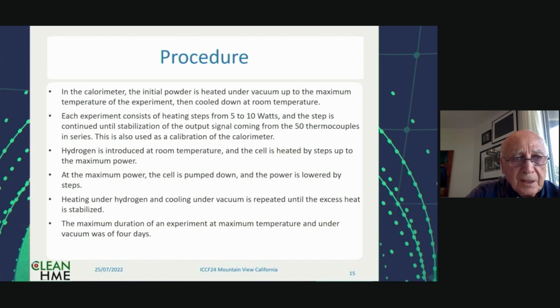Okay, so what to do? The initial powder in the calorimeter is heated under vacuum up to the maximum temperature of the experiment, and then cooled down to room temperature. Why do we do that? This is good because it also helps as a calibration of the system, because there's nothing active, so the calorimeter can be calibrated this way. The calorimeter doesn't give you exact power. You have to calibrate it before.